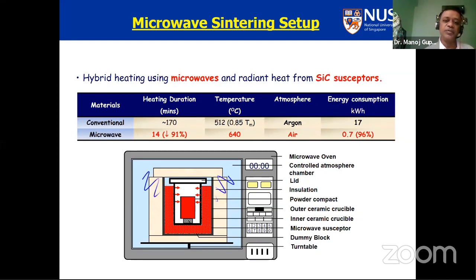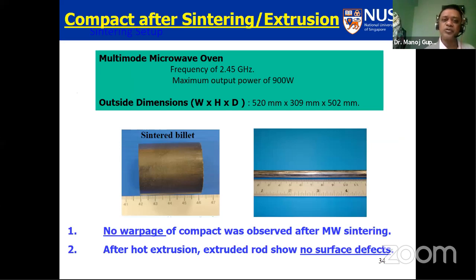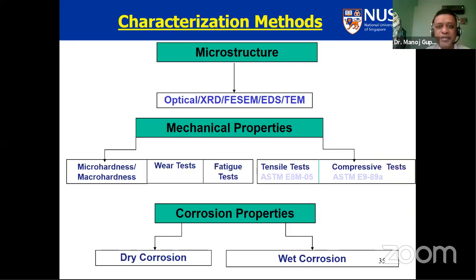And you get a very uniform temperature distribution, which leads to very good microstructural uniformity. This slide shows the specification of the oven, which is a household oven, and you can extrude the billet, no problem. You get properties similar or better than conventional sintering, as per our work done some time back.